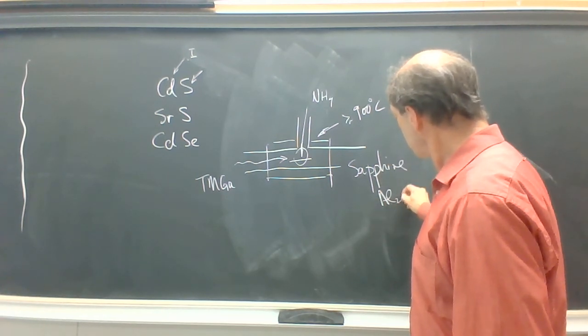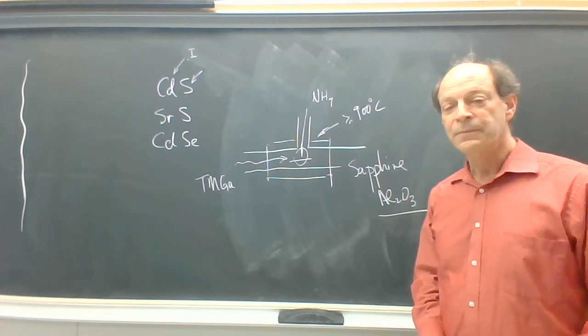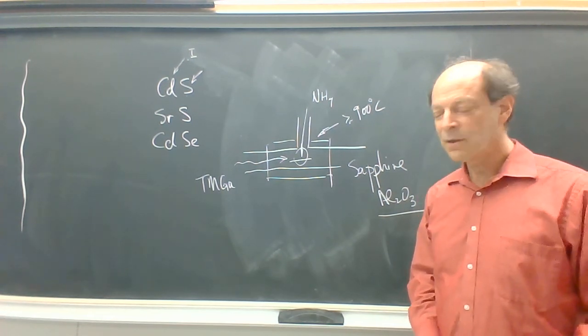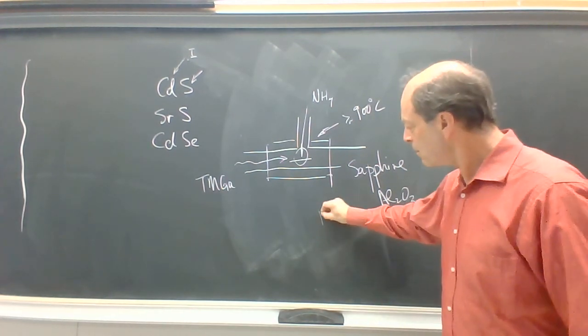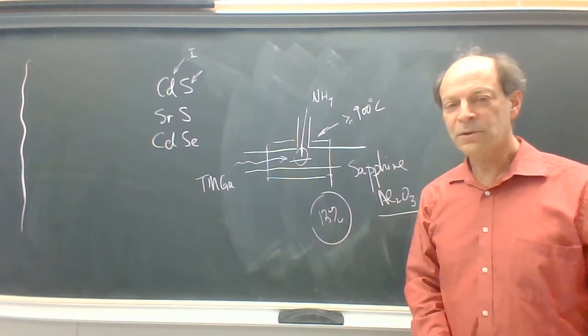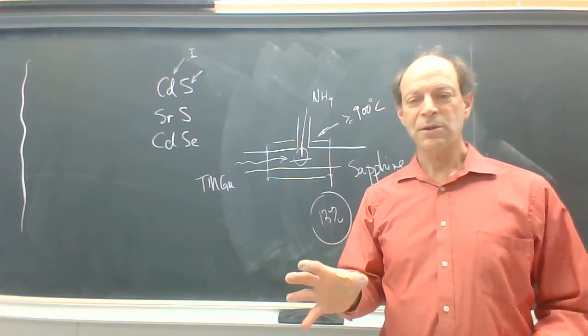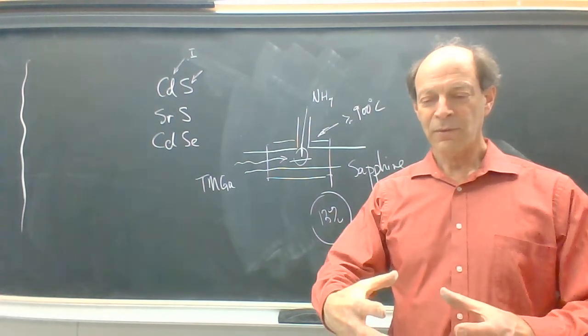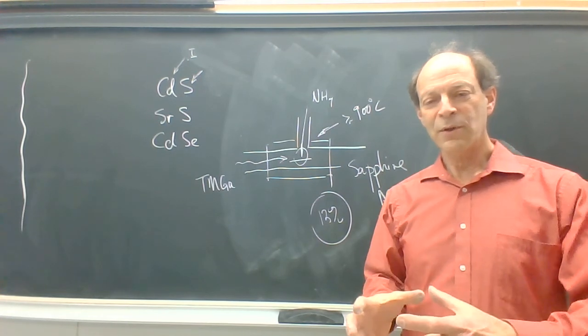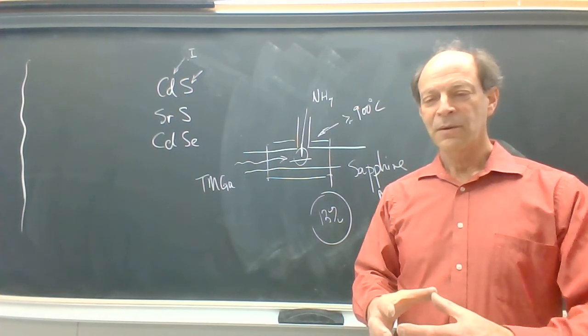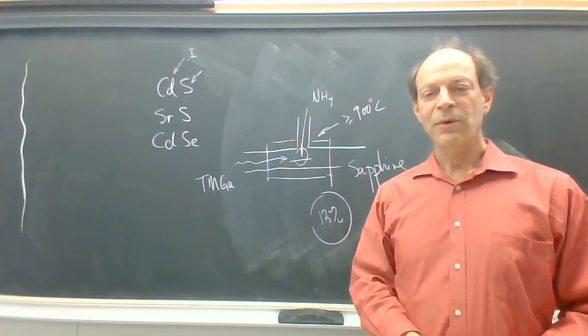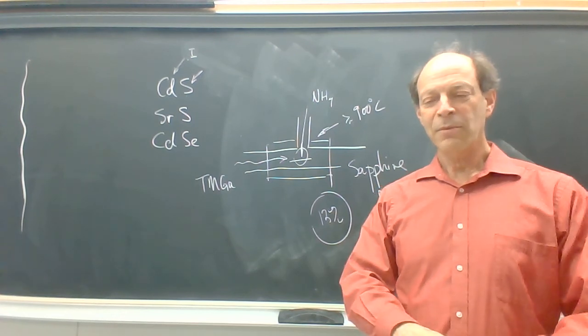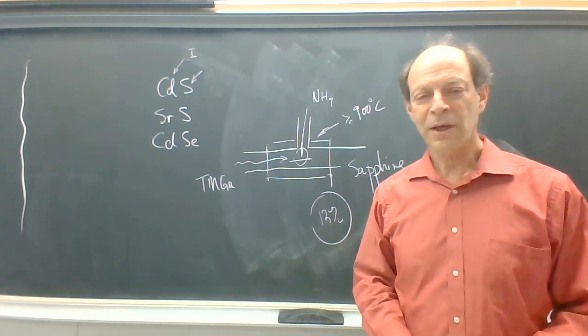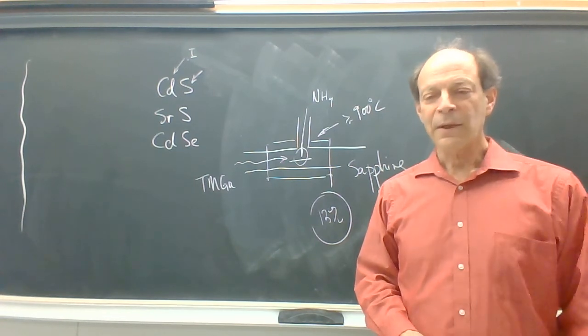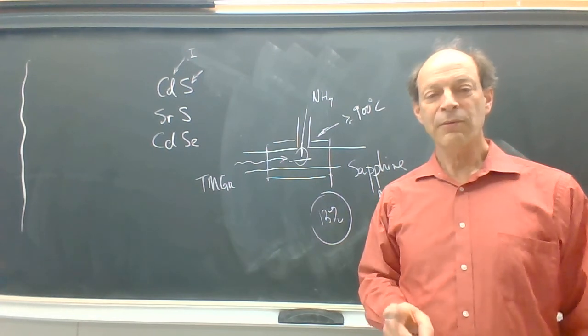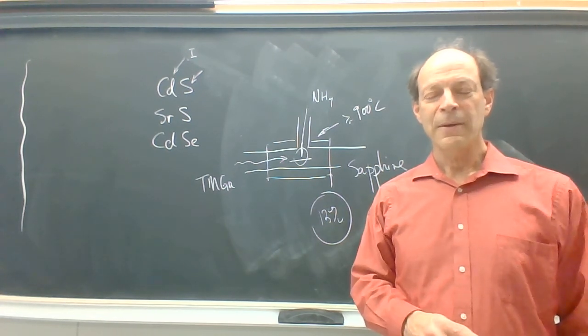And sapphire, or aluminum oxide, is not lattice matched with gallium nitride. Its lattice constant is far different. It's about 13% different. So you have a huge lattice mismatch, but nevertheless, this one researcher in Japan found that the gallium nitride, if it actually rotated to a certain tilt angle on the substrate, could grow surprisingly large single crystal regions. And there were far fewer defects in the gallium nitride film than might be expected from such a huge lattice mismatch. So Nakamura immediately turned to aluminum oxide because he recognized the technological benefits of a substrate which